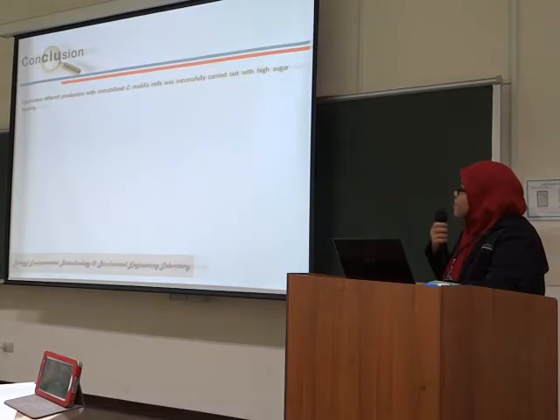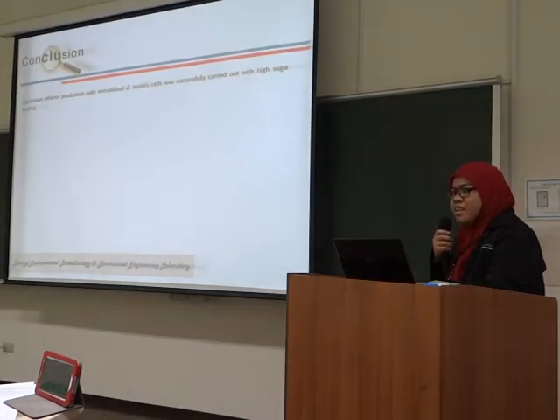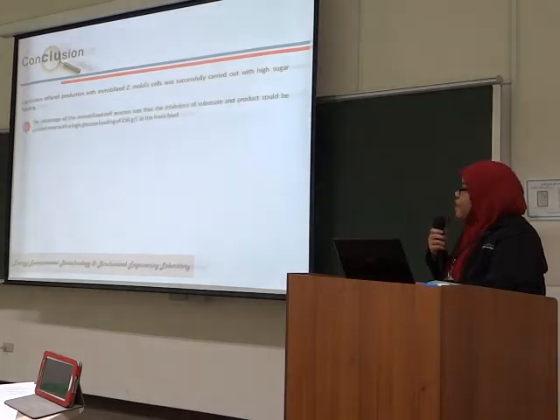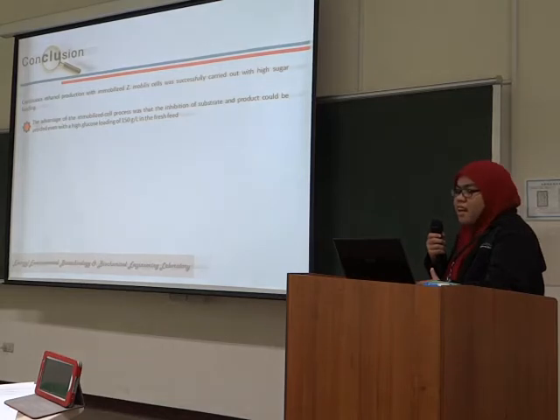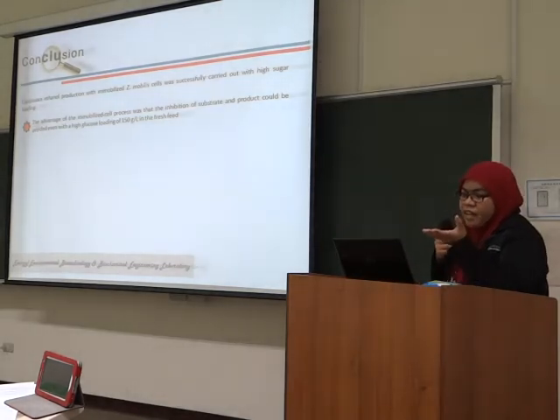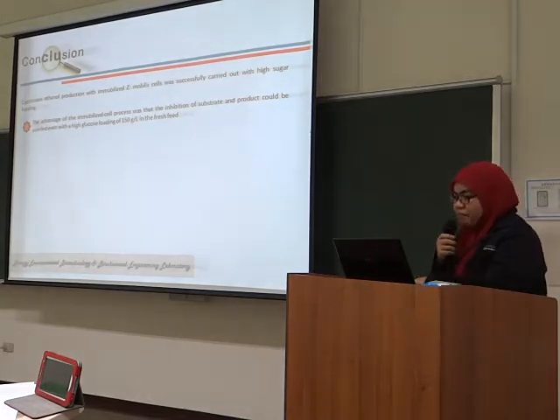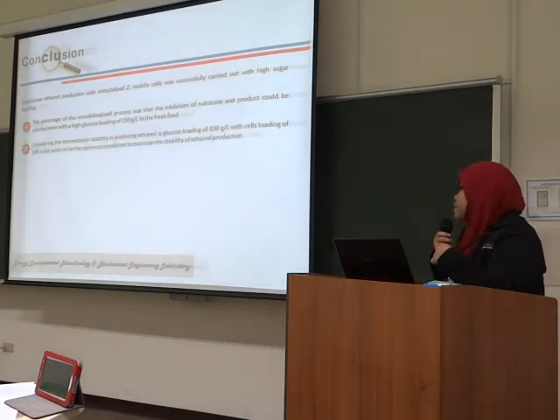So, in my conclusion, I think this study should be considered successfully carried out with high sugar loading up to 150 gram per liter with ethanol production 79 gram per liter. And if we see the advantage of this modification, it can overcome both substrate inhibition and also product inhibition. And then if we consider the stability of the fermenter or the stability of the strain that we use, 100 gram per liter of glucose loading should be the optimum condition. And it can maintain until 1 month of operation.